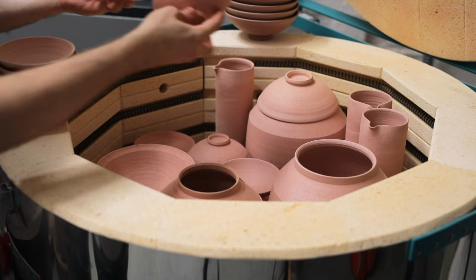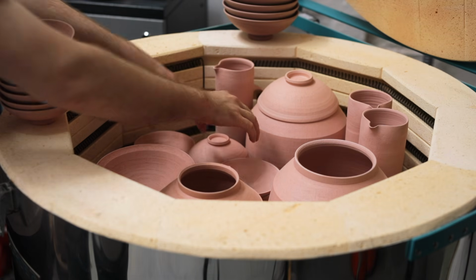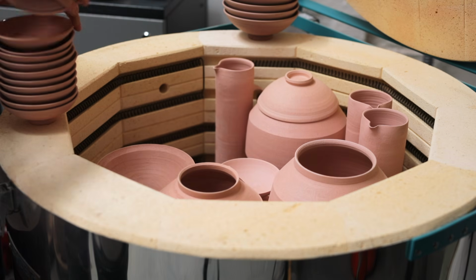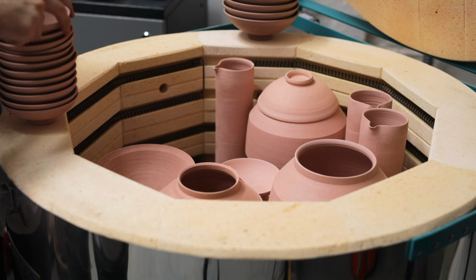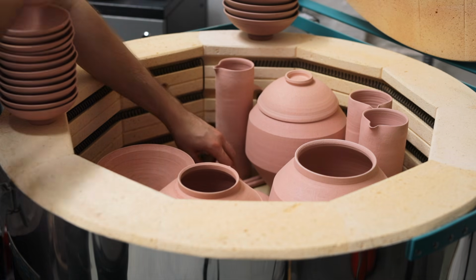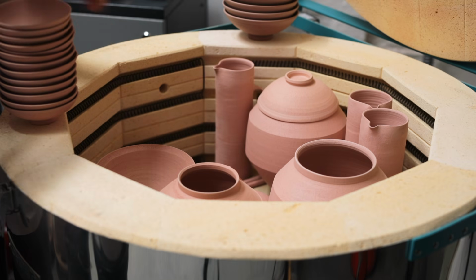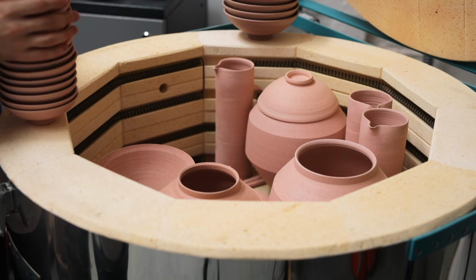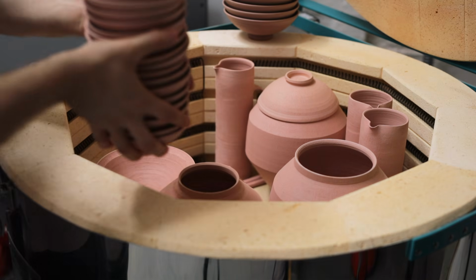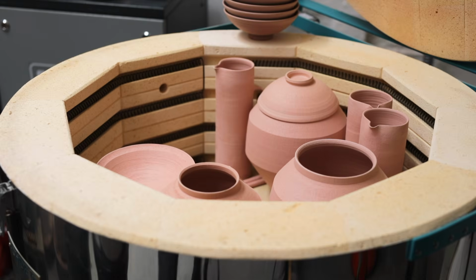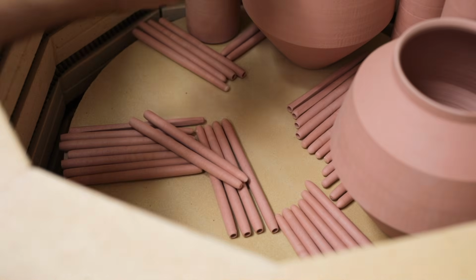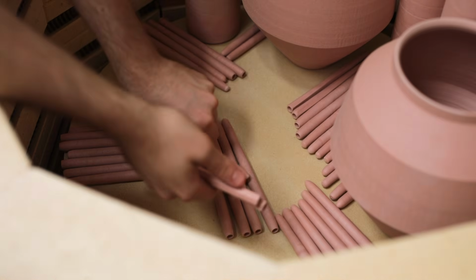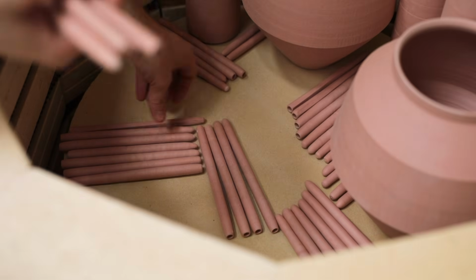But you can see here just how much more brazen I am in the handling of these pots. Previously, when bone dry, I could never stack them like this, but that isn't to say they're very strong, because they aren't. Even if you grip a bisque-fired pot too firmly, it's possible to break them and crack them, especially if they're made thinly. So you do, at this stage, still need to be very careful about how you handle the pots and move them around.